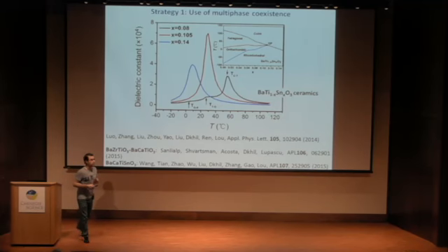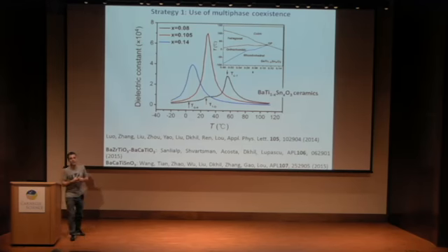And this is true because look at this dielectric measurement, and you see that the dielectric constant is highest compared to the left side or the right side composition. This dielectric constant tells you that the dynamic of the dipole is higher than in the blue or black cases. So you have an indication that this composition might be very interesting for calorics.